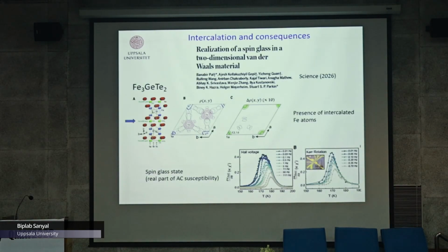So now what I want to say is about the intercalation of these magnetic atoms in these systems. Recently there is a paper I just want to highlight from Stuart Parkin's group. They have shown this for iron 3 germanium telluride systems. So this is basically the system. These are the monolayers. You have the tellurium atoms, then some iron atoms, germanium atoms, and then there is a van der Waals gap here, and then the second layer comes in. This is a typical bulk unit cell of iron 3 germanium telluride. But what they have shown is that there are iron atoms in the van der Waals gap.